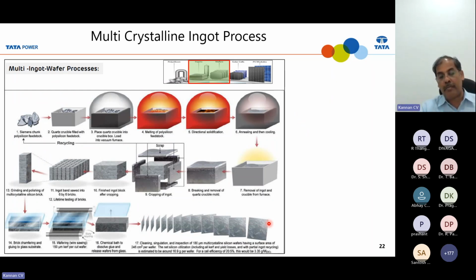But unfortunately, this is the multi-crystalline wafer. So the overall manufacturing cost will be relatively lesser, but the quality of the wafer is relatively poor. So maybe 2 to 3 years or 4 years before, this was the dominant growth method in the industry. But now the industry demands very high quality wafer. So through this technique, you cannot grow beyond a certain quality. So that's why this method is almost phasing out of the market.